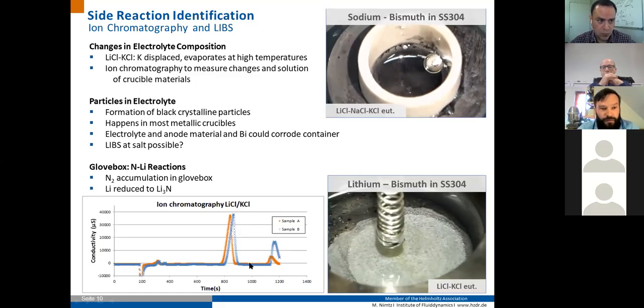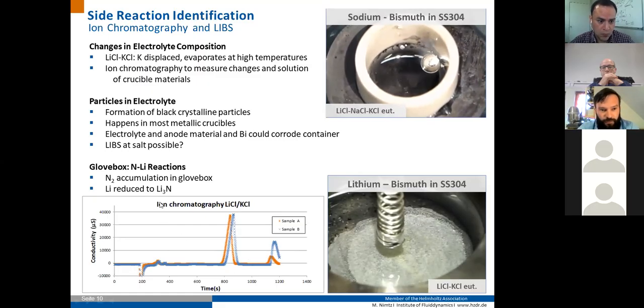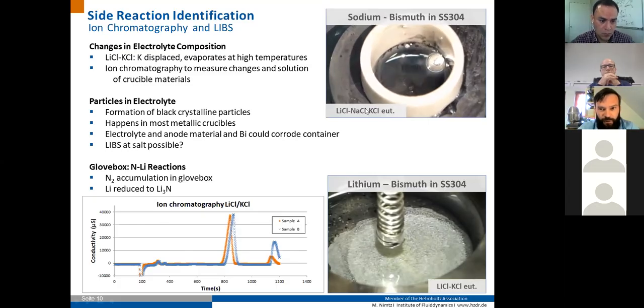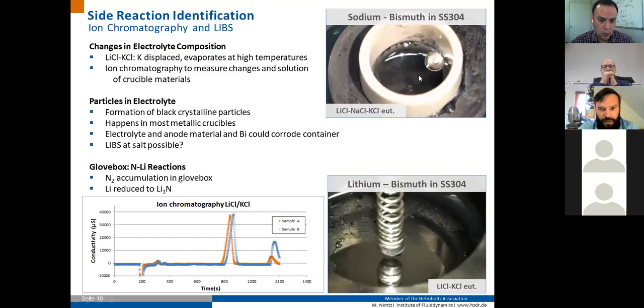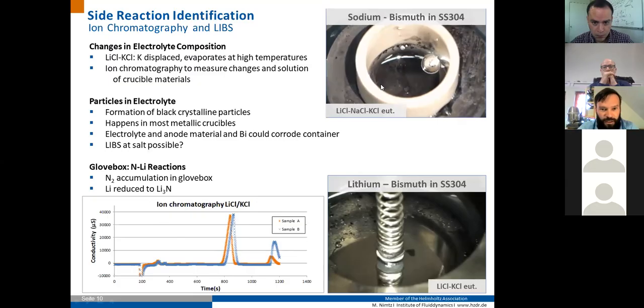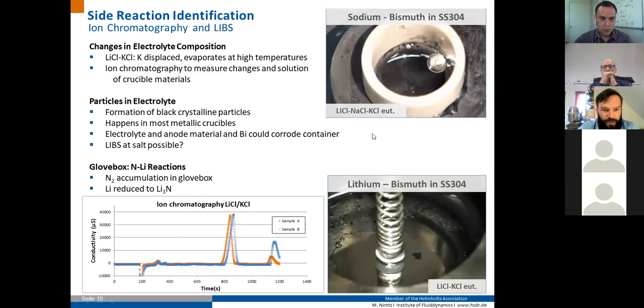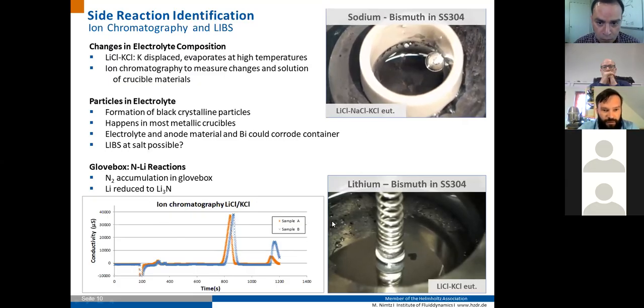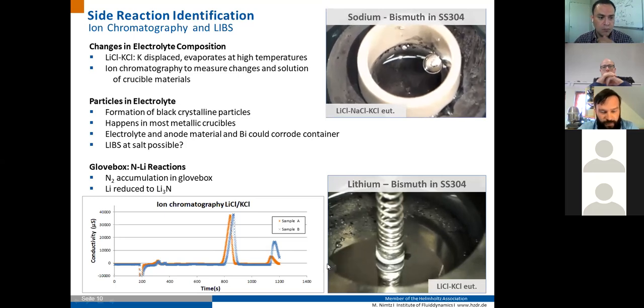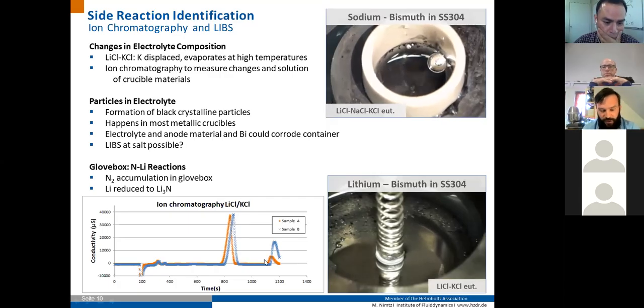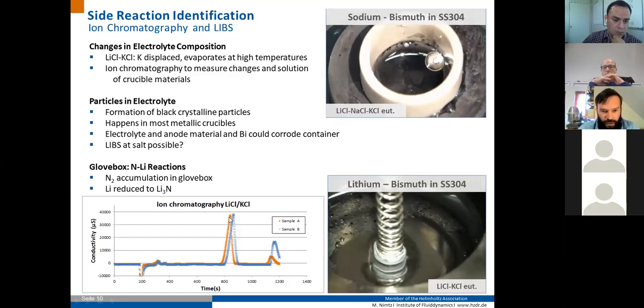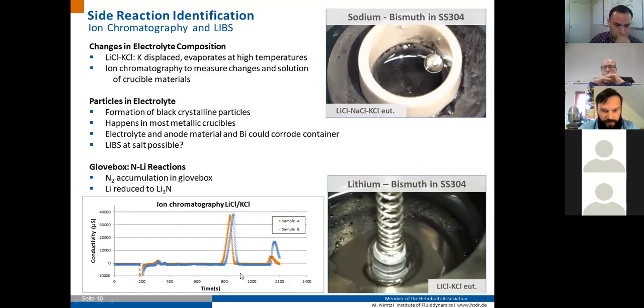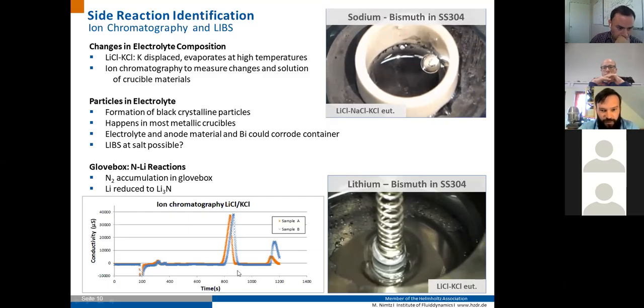To get an idea of what happens, we tried to observe the electrolytes. There were some black crystalline particles forming as well, and to get an idea about other side reactions, for example, with the change in the electrolyte composition, we used ion chromatography to identify the shift in composition during cycling of these experimental cells.